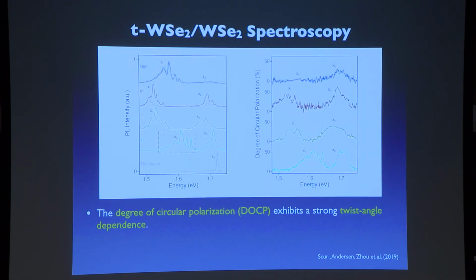That's nice. But one interesting thing is the following. If you measure the so-called degree of circular polarization of these peaks, they exhibit interesting variation as a function of the twist angle. So basically, what we are measuring here is the following. We shine right circularly polarized light into the sample and measure whether right circularly polarized light comes out or left circularly polarized light comes out. If the same circular polarization comes out, then the degree of circular polarization is high. And you can see that in the natural bilayers, there is no degree of polarization for the interlayer excitons, while for the twisted angles, there is a high degree of circular polarization.